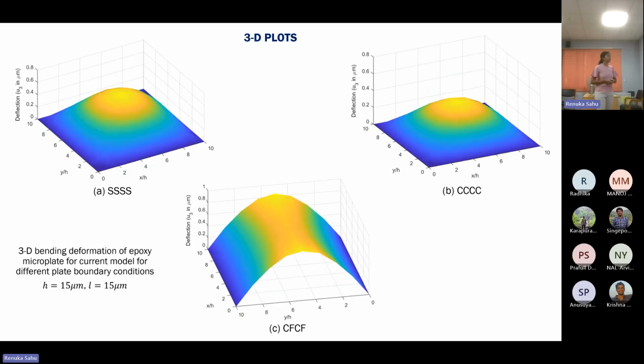We have also obtained the 3D bending deformations of the epoxy microplate for the current model and for different boundary conditions. The plate thickness H and the material length scale parameters are kept the same in all of these models. You can see the least deflection is given by the all edges clamped case, then the all edges simply supported, and the clamped-free two edges clamped case gives the higher deflection.